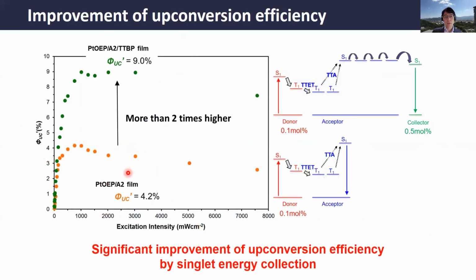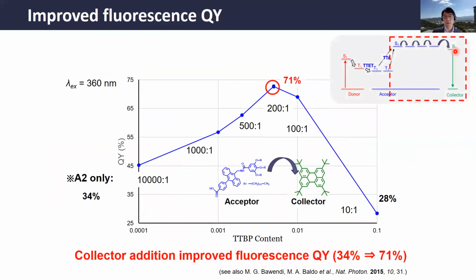So this two-component donor-acceptor system shows 4% upconversion efficiency, and by just adding a small amount of collector, we observe more than 2 times higher upconversion efficiency. This is partly because of the improvement of fluorescence quantum yield, as pointed out by Baldo's group in 2015. The original acceptor-only film shows a fluorescence quantum yield of 34%, and it increases to 70 or 71% by adding this collector. So you can avoid concentration quenching by using this isolated collector.